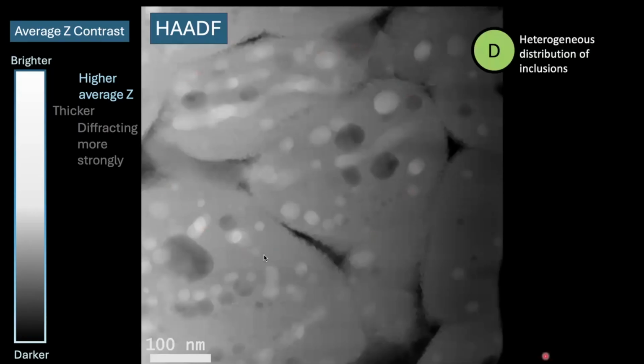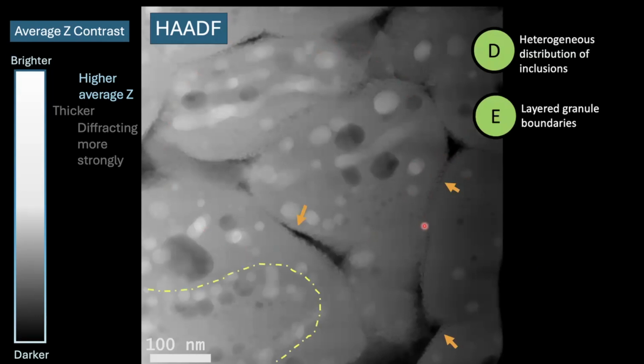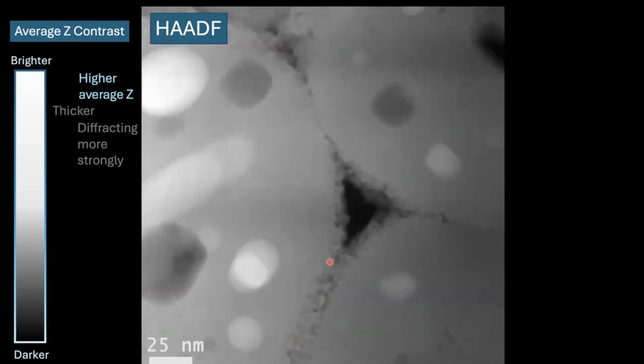For the most part, they're all over the place, and there really are a lot of them. We also have layered granule boundaries. First I'll mention this is something I'm going to talk about later for the inclusion poor region. But those layered granule boundaries look like this, and this is something that has been noted before for granular zircon. This is just a close-up. Some of them are really crummy looking, but mostly you can see that those inclusions really are inclusions. It's not like you have a huge amount of zirconia and silica exterior to the granules.